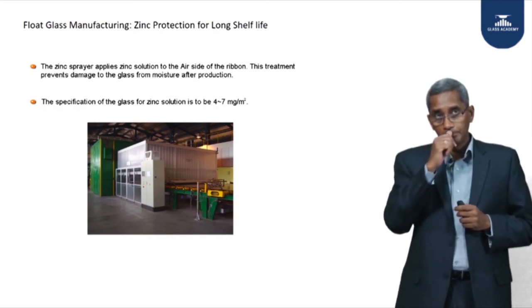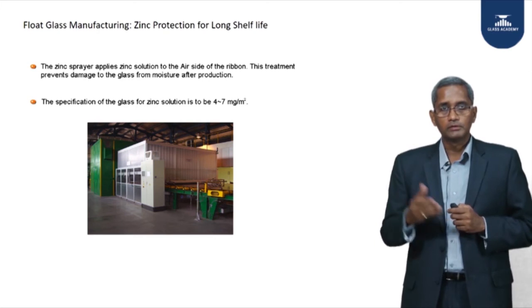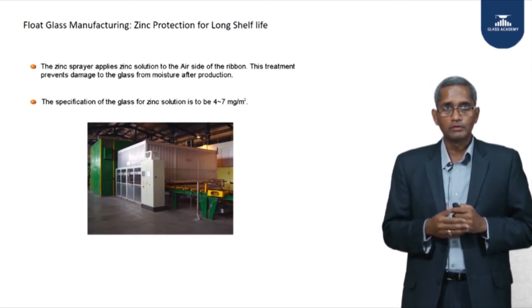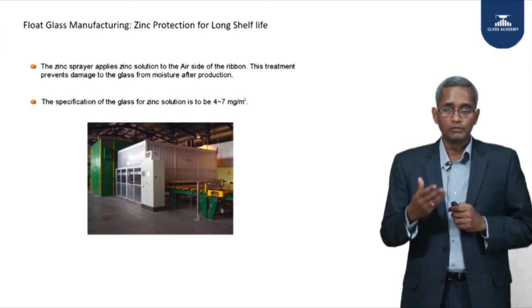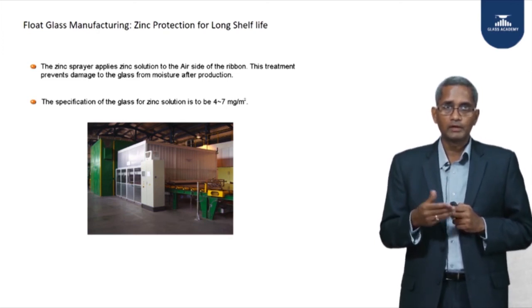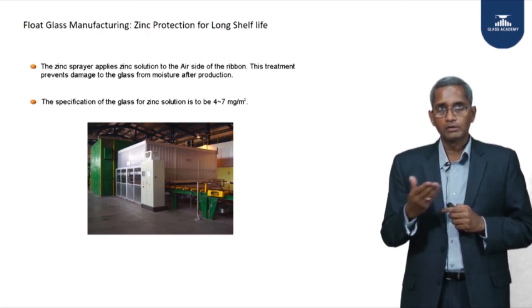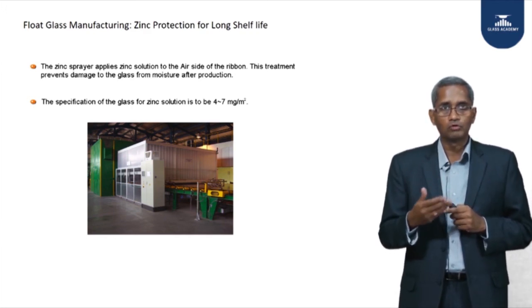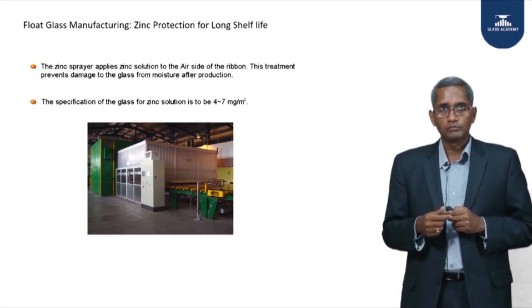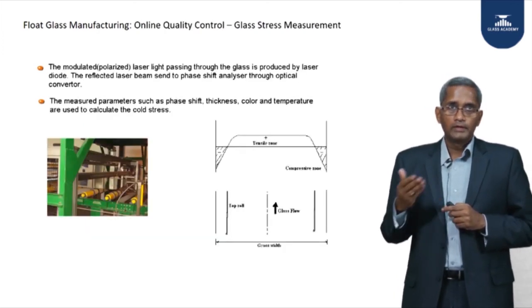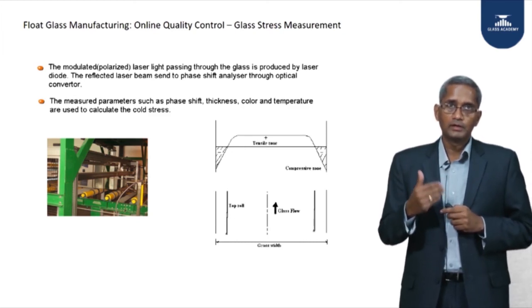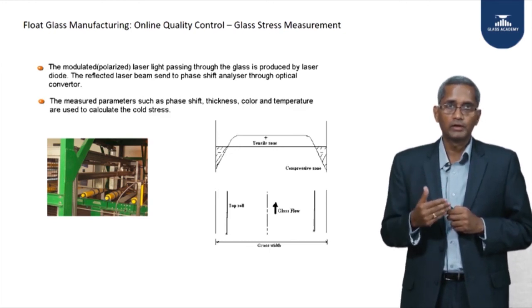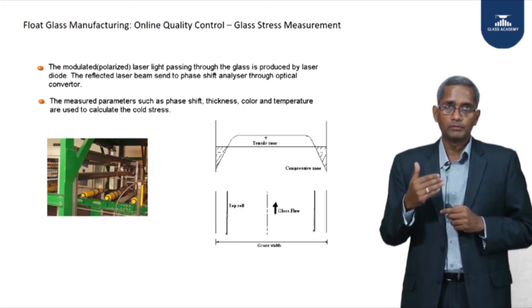The glass is cooled to 60°C. To meet customer requirements, the glass is sprayed online with zinc solution to protect against weathering from humid conditions during warehouse storage. Online equipment continuously measures stress on the glass so we can regulate and avoid sending high-stress glass to customers.